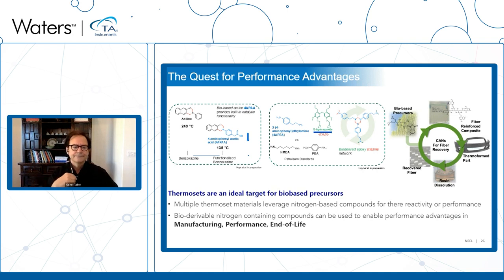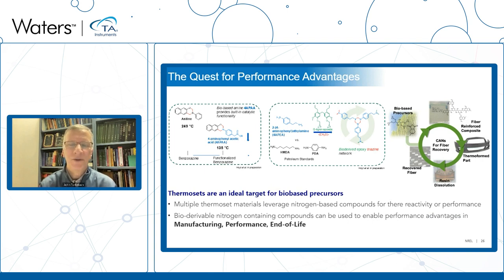Yes, so that's a very important question. We ended up making use of compression molding equipment for doing the reprocessing because we're in a university environment where small scale equipment is what we have to work with. However, we did the reactive mixing with that, in terms of a process that has actually been shown to be an effective substitute for things like a twin screw extruder. Now, the time scales associated with our process for what we have currently done are too long in terms of a typical twin screw extruder operation with the temperatures we'd have employed.